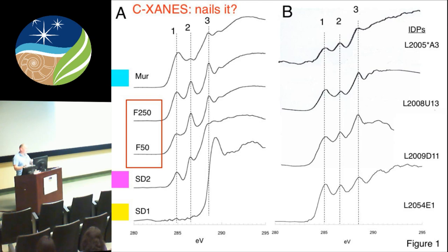So we do a lot of work trying to understand the XANES spectra. What I'm saying is, these look very similar, but they're actually fairly significantly different, particularly in the quantity of this carbon. The other thing about NMR, which I didn't want to dwell on, but I could talk about NMR for years if you let me. But XANES, like most spectroscopies, is subject to uncertainties about what's called the absorption intensity. It's not something that you can predict a priori. It's related to a number of factors relating to the transition dipole matrix element magnitude from a ground state to an excited state.